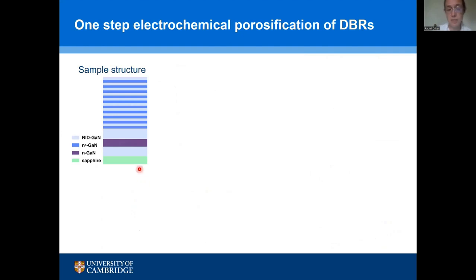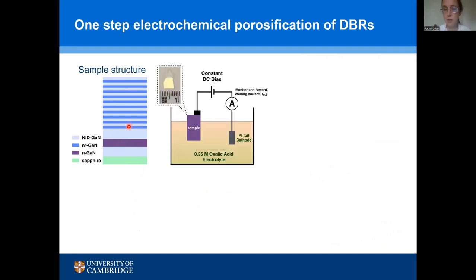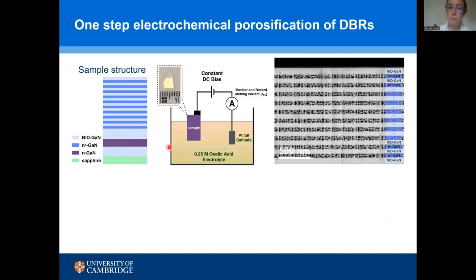And we grew, in this case on A-plane GaN, these alternating layers of highly doped and undoped gallium nitride. And we etched those in the sample setup I showed you before. And this is the kind of distributed Bragg reflector that we can achieve. So we've got our non-porous GaN layers and then our porous GaN layers alternating up the stack with nanoscale porosity. Now, that's not new. We weren't the first people to do this, but there are some interesting differences between our process and the processes that have been used elsewhere.